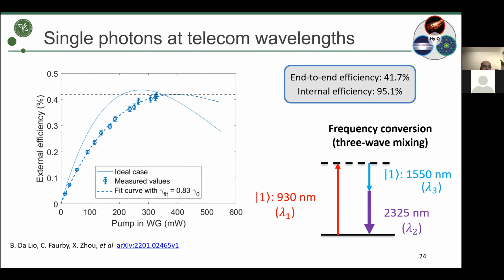Now, I would like to open a small parenthesis about something that we have done very recently that I'm quite happy and proud of. We've also shown that we can generate these photons at telecommunication wavelength. The quantum dots, as I mentioned, produce photons at 930 nanometers. 930 nanometers is not a good wavelength for telecommunication because light gets absorbed a lot in a fiber. I think the loss is around 3-4 dB per kilometer. But if you could work at 1550, which is the typical telecommunication wavelength, then this absorption will go down and you will have losses on the order of 0.2 dB per kilometer or so.